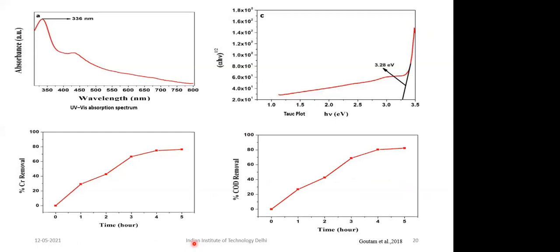So even the optical properties of the synthesized green nanoparticles were determined from the absorption study, and the band gap of the photocatalyst was obtained by plotting the Tauc plot. The Tauc plot is nothing but, once we have synthesized the nanoparticles or the nanophotocatalyst, we have to determine the band gap of the synthesized photocatalyst. That is important because we have to compare the synthesized plant-based photocatalyst with the ordinary or conventional nanoparticles which are available in the market. So it will be almost a similar band gap, or sometimes even studies have reported a reduction in the band gap too. So that is showing effective catalytic properties of the synthesized plant-based photocatalyst. Also, the reduction in chromium as well as the COD reduction shows the potential of the synthesized green photocatalyst. So the study has effective proof to show that the plant-based photocatalyst can be effectively used for the degradation of organic contaminants.